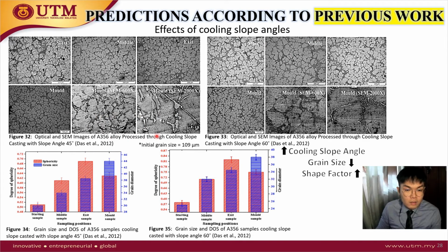So this previous work uses two different angles, 45-degree and 60-degree, and this is the result. The degree of sphericity is also known as the shape factor. It is the same thing. So from here we can see with 60-degree slope angle, the shape factor is higher and the grain size is smaller.